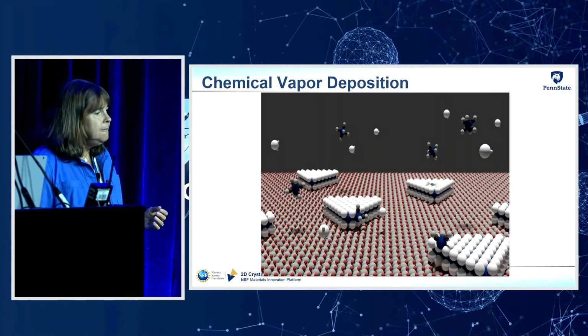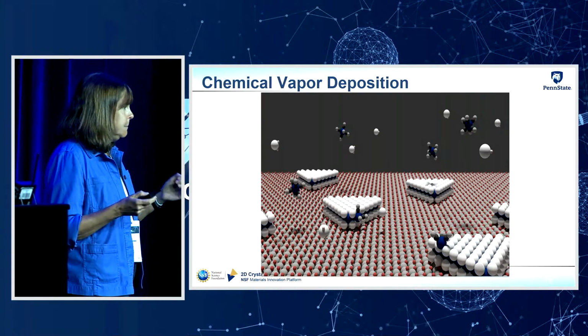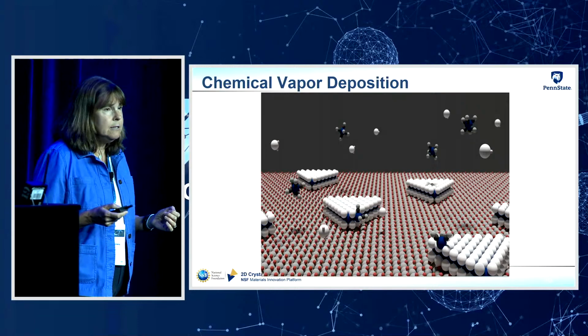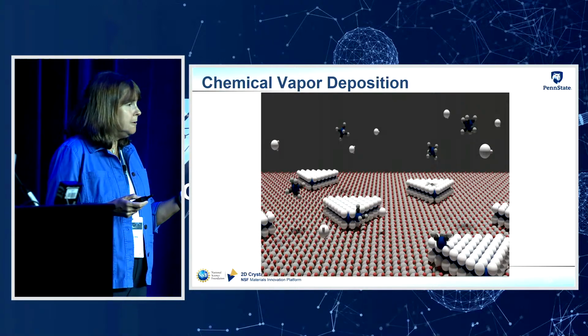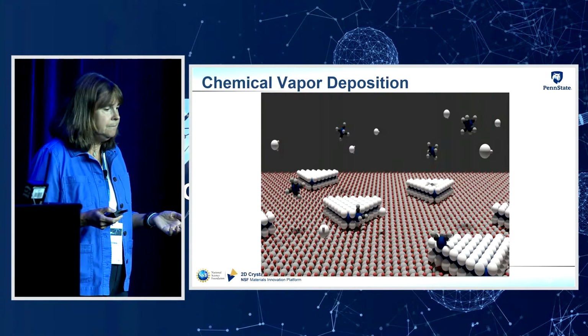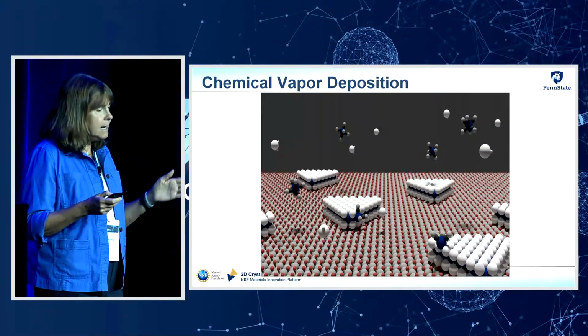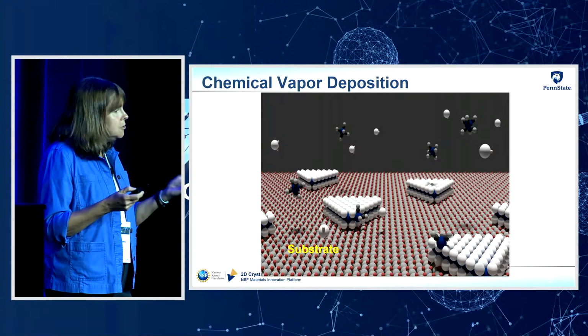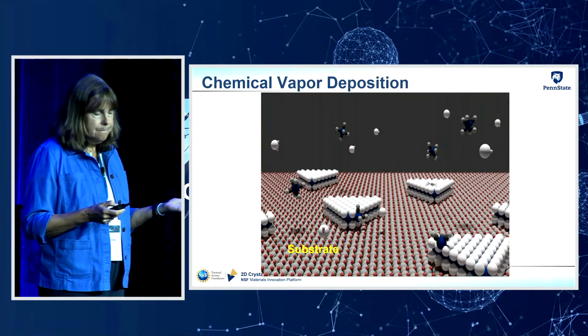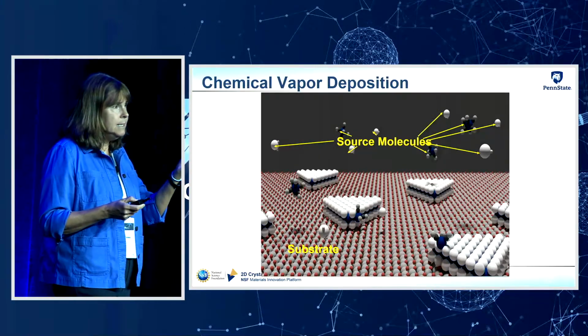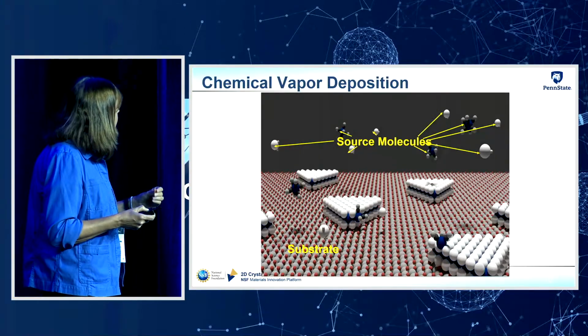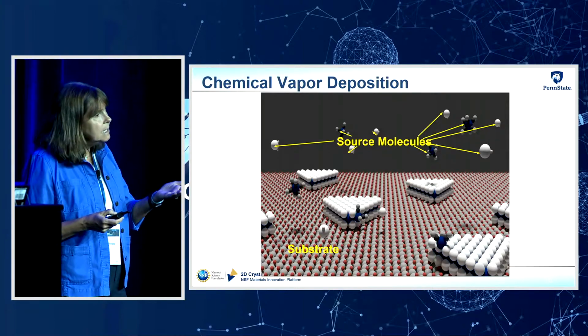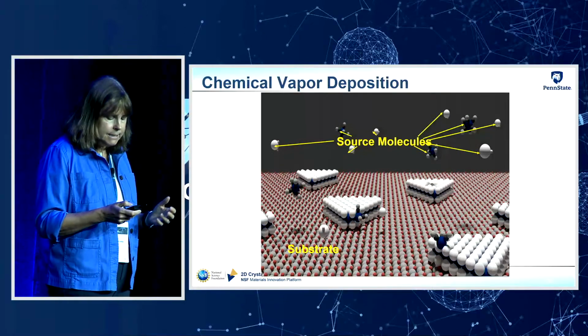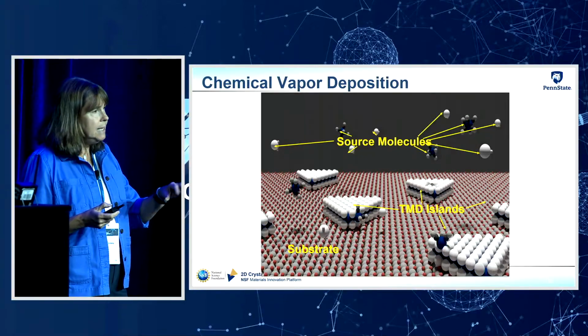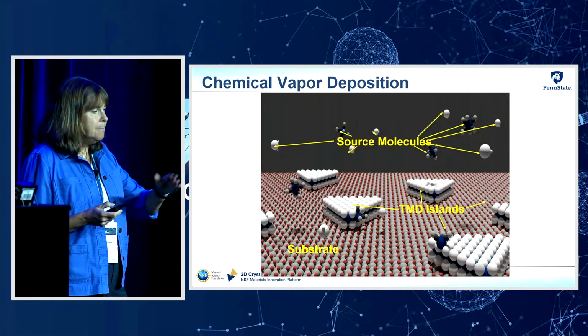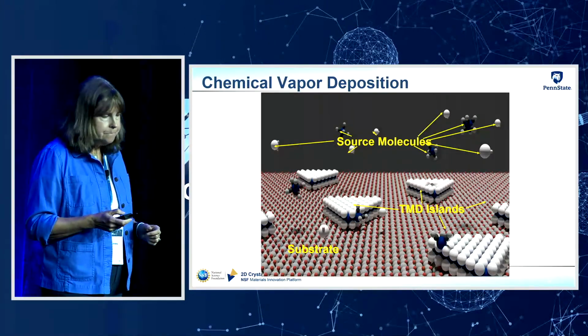So instead, there's been a lot of focus and a lot of interest on using vapor phase deposition methods. And the most popular technique that's used to deposit monolayer films of TMDs is chemical vapor deposition. So just to show you this technique, for those of you who aren't familiar with it, you start off with a substrate where you want to deposit your film. And then you have source molecules that contain elements of the film that you're depositing. You introduce these in the vapor phase. They get heated as they approach the substrate. They start to react and decompose. And then you end up nucleating islands on your substrate, in this case, TMD islands.